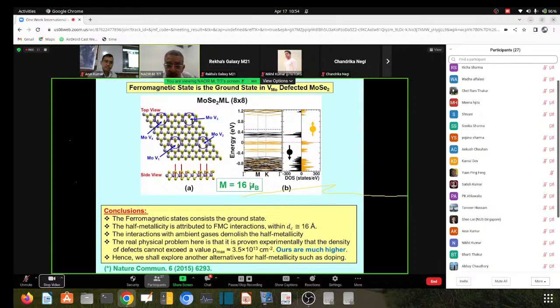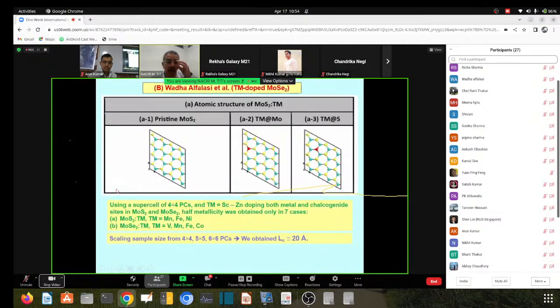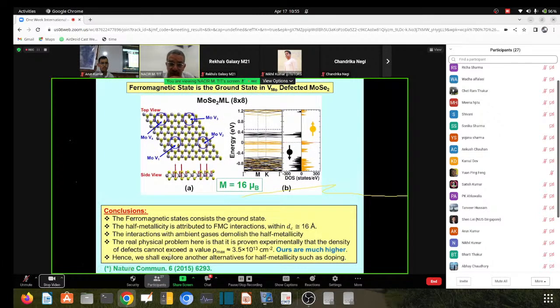Anyway, I said probably in the beginning I'm not going to finish describing everything, but now I will move to the paper of Wadha on transition metal doping because it's more promising. Here we have an inconvenience, like I said: the density of vacancies is experimentally proven to be 3.5 times 10 to the 13 per centimeter squared, which is the maximum density that can be in the samples. Whereas ours needs more density, because one vacancy per 4x4 sample requires high density. So we don't have it experimentally available. So what to do? It's better to explore doping.